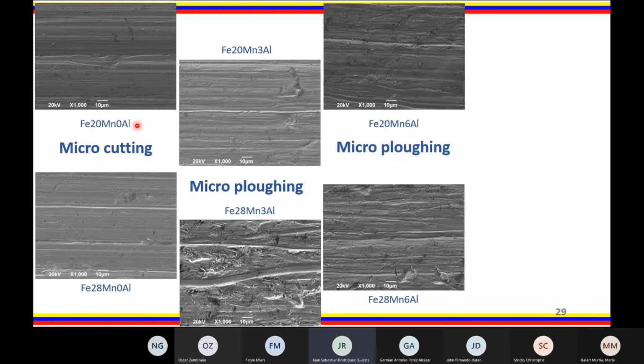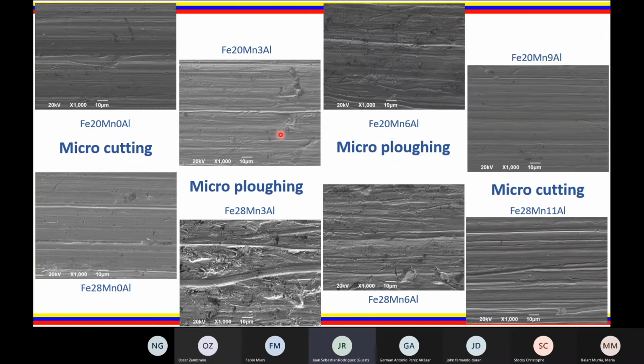In the analysis corresponding to the wear surface, we find something quite interesting: the low hardness steel, zero aluminum, and the high hardness steel, 9 aluminum, low aluminum and high aluminum, in general terms, present microcutting, while the medium aluminum ones present high microplowing. This serves as evidence to continue with the hypothesis that plasticity hardening mechanisms improve wear resistance at the surface level.